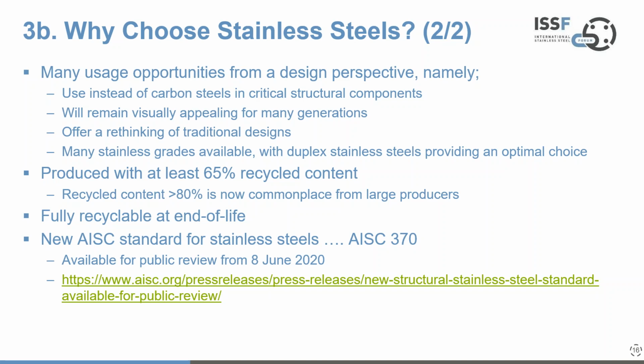Now, in addition to those points, the usage opportunities give you some interesting design issues to consider. First and foremost, in saying what I'm going to say now, this is not about stainless steel trying to take over from carbon steels completely. That would be crazy. But in critical structures, replacing carbon steels for stainless becomes highly valuable, because then you prevent failures. And if you identify where things are going to corrode, replace them with stainless, you will certainly prevent failures. I've talked about the visual appeal, and a great case in point is the Chrysler building in the USA, which has had stainless steel cladding for almost 100 years and has been washed twice with a normal household detergent.